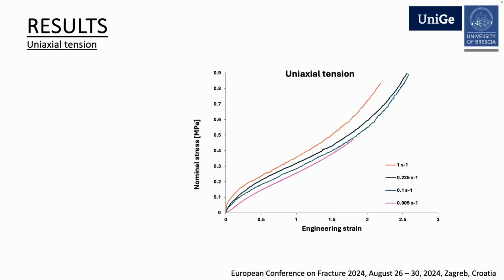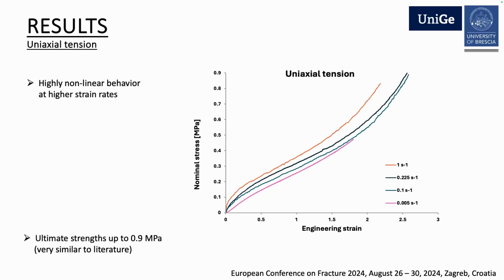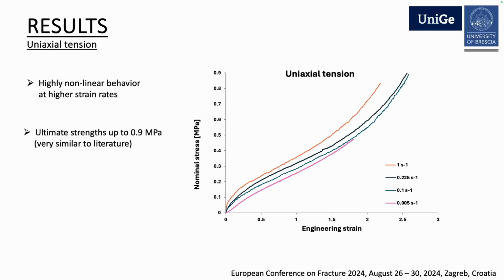Now, coming to the results, considering uniaxial tension tests at different strain rates, we can see that, as may be expected, the behavior is highly nonlinear, and globally, the response seems to get stiffer as the strain rate increases. On the other hand, we also observed that the ultimate strain at failure showed some dependency on the strain rate, and actually the test that provided the lowest strength and the lowest ultimate strain was the one that was carried out with the lowest strain rate.